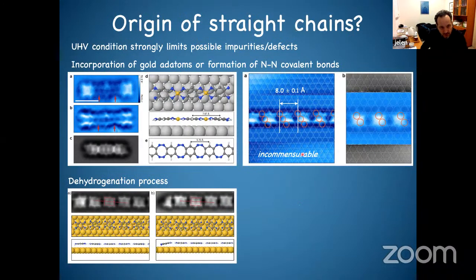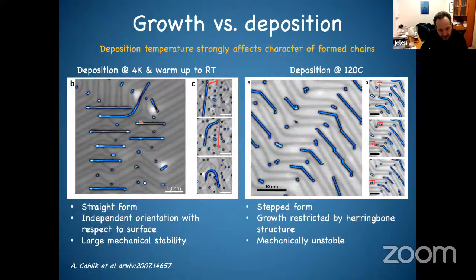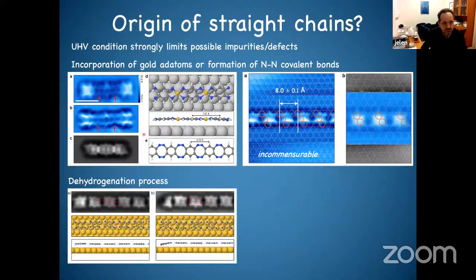So now you can ask, okay, maybe what happened is we deposited at room temperature, and now maybe there is some gold atom in between, and you create an organometallic chain. So it would be something like that, okay? Or you lose all hydrogens, and now you have something like this. This could be excluded by the fact that the lattice vector of this chain is much shorter than what we observed. And the second thing is, when we consider this gold here, it has a very similar lattice distance as the original one.